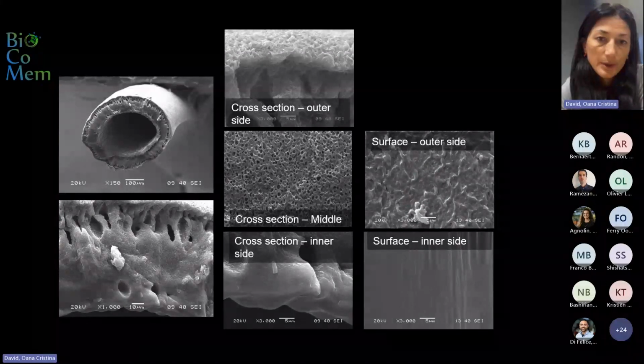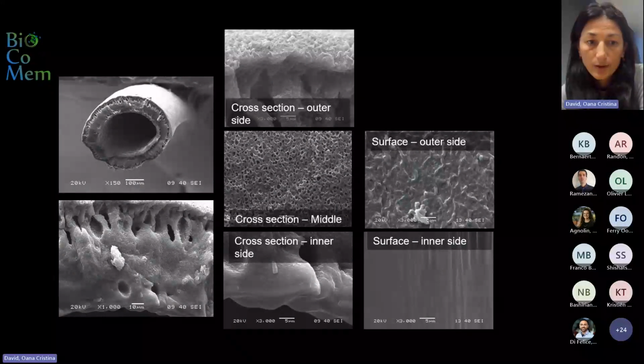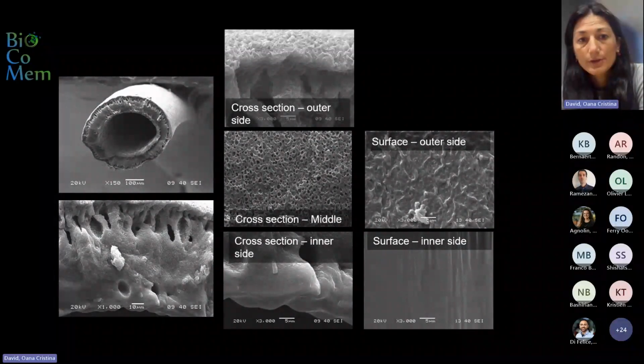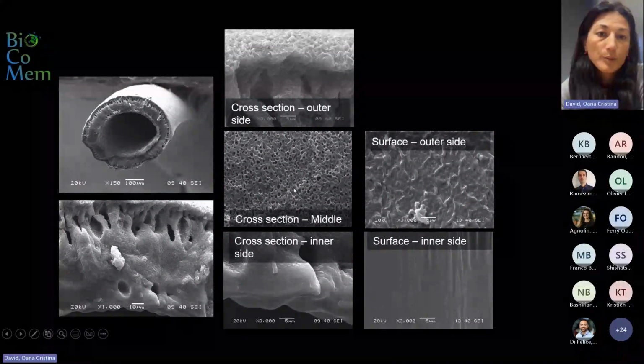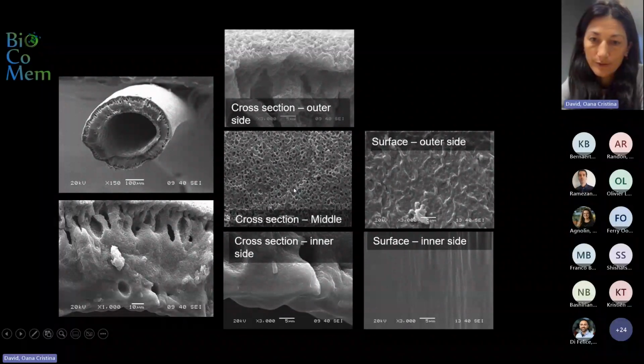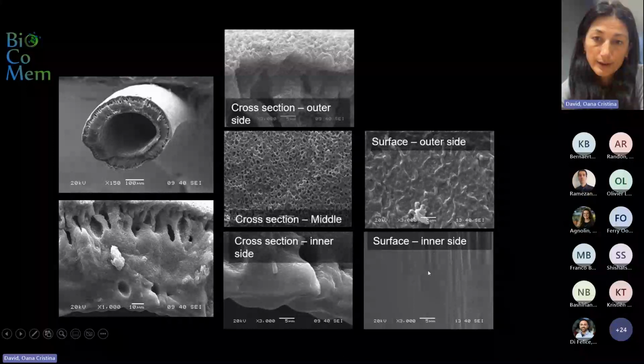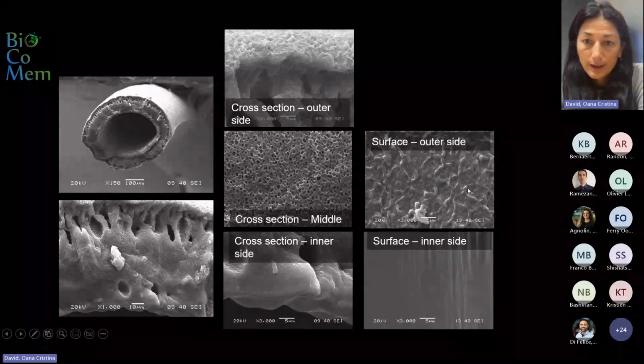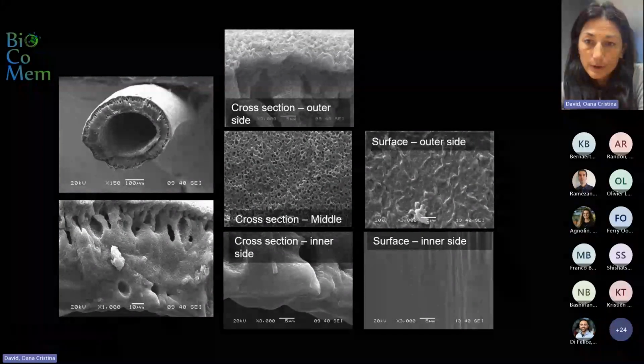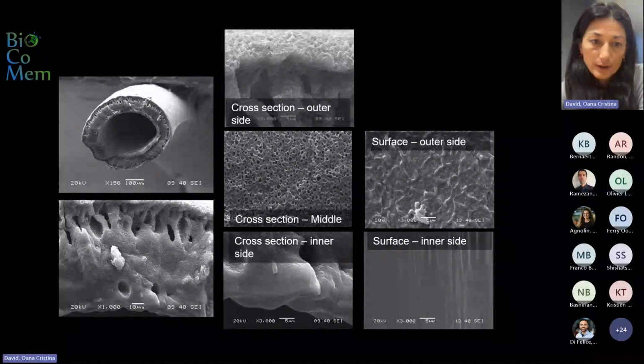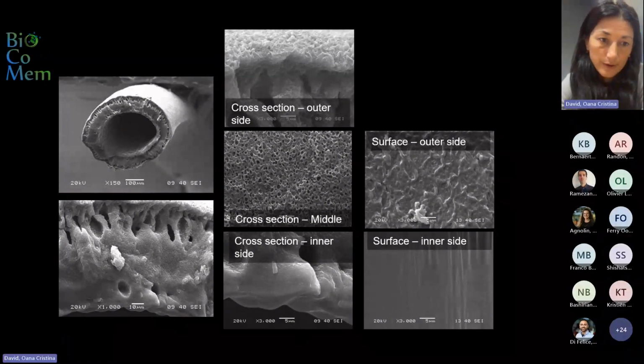So with these results, we decided that we should scale up this polymer. These are a few SEM images of these first results. They do not have an optimized structure, but we did have some porosity in the middle side of the fibers. At the inner side, we have a dense layer, and at the outer side, we should have a very nice porous layer, but these were the first experiments, with a lab scale batch. So we decided to scale up this polymer.